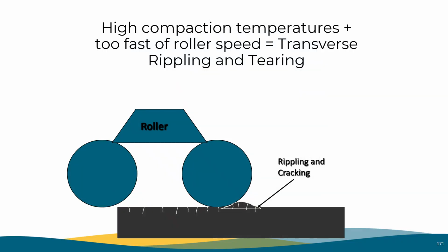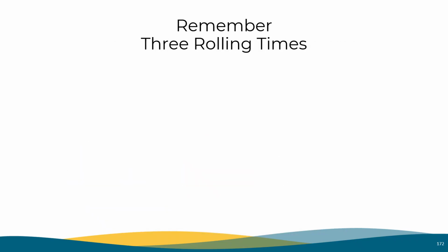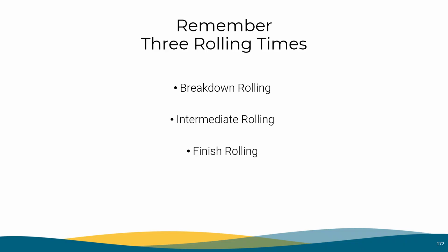Also, with high compaction temperatures and too fast of roller speed, transverse rippling and tearing can occur. Remember these 3 rolling times: breakdown rolling, intermediate rolling, and finish rolling.